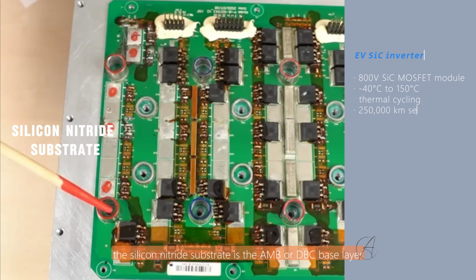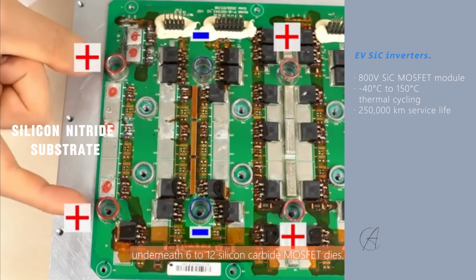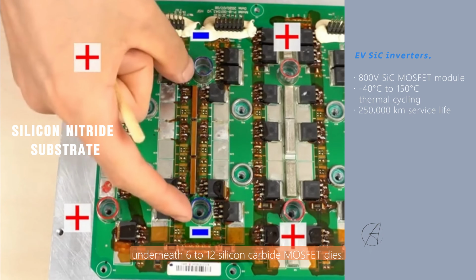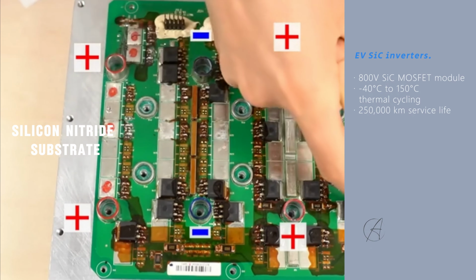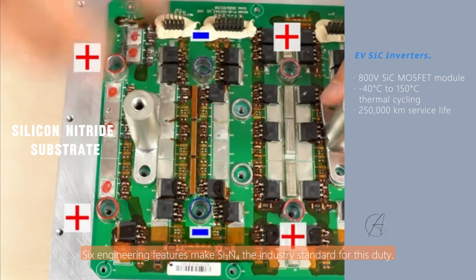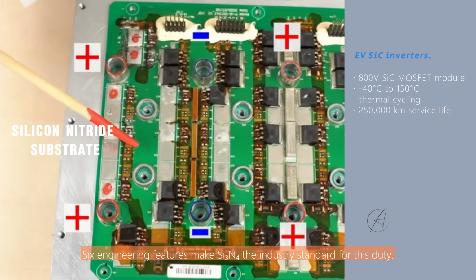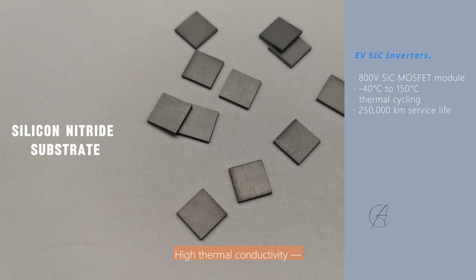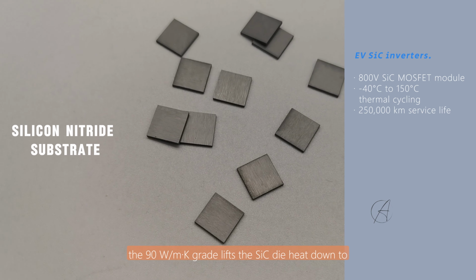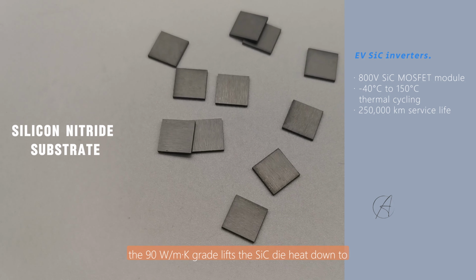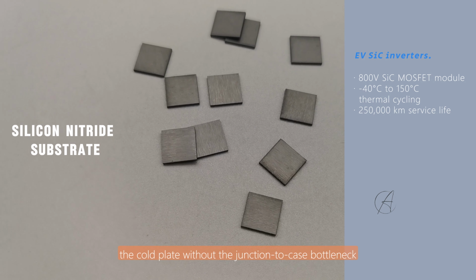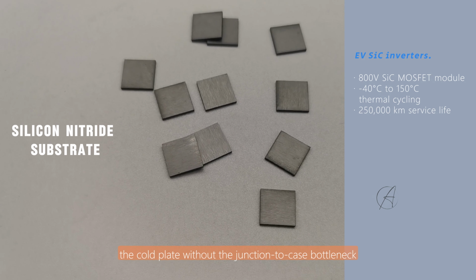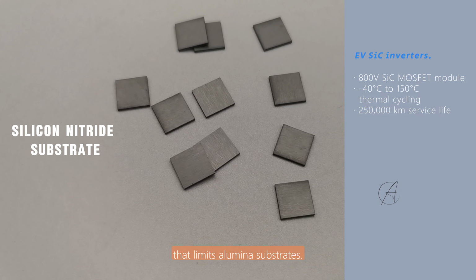Inside an 800-volt EV traction inverter, the silicon nitride substrate is the AMB or DBC base layer underneath 6 to 12 silicon carbide MOSFET dies. Six engineering features make silicon nitride the industry standard for this duty. High thermal conductivity. The 90 watt per meter per Kelvin grade lifts the silicon carbide die heat down to the cold plate without the junction to case bottleneck that limits alumina substrates.